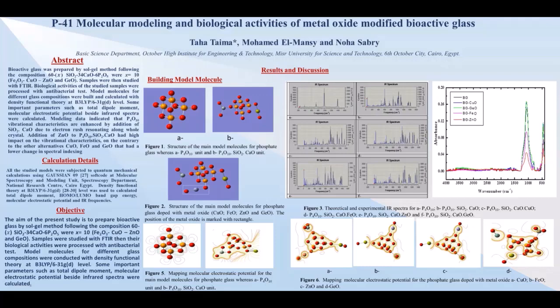Bioactive glass was prepared by sol gel method following the composition 60 silicon dioxide, 34 calcium oxide, 6 P2O5, where X equals 10 from Fe2O3, copper oxide, zinc oxide, and germanium oxide. Samples were then studied by FTIR, and biological activities of the studied samples were assessed with an antibacterial test.